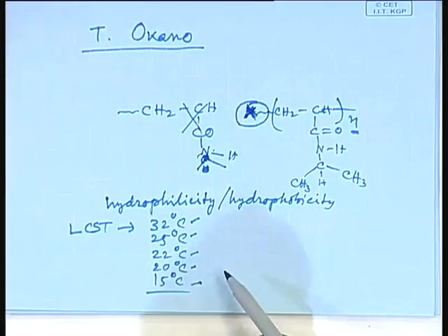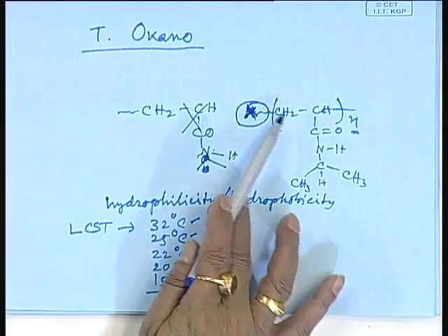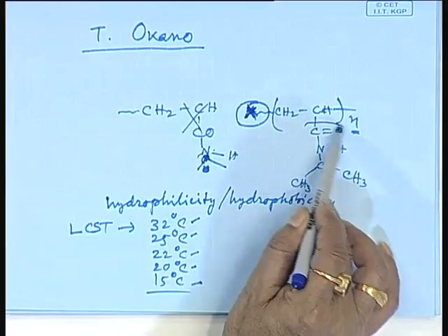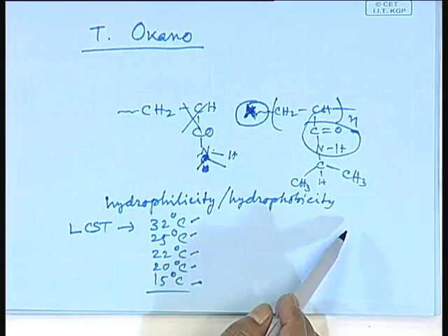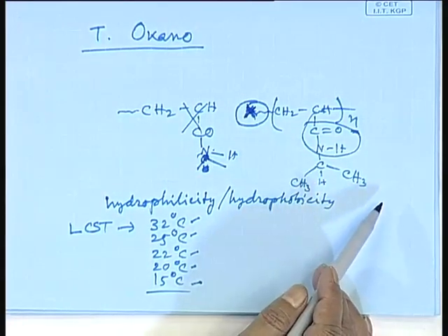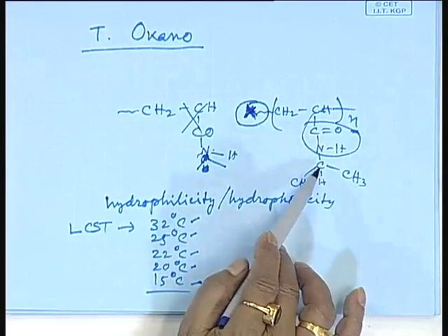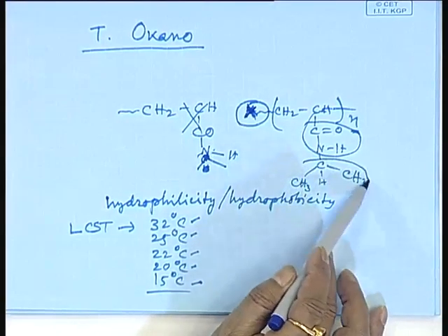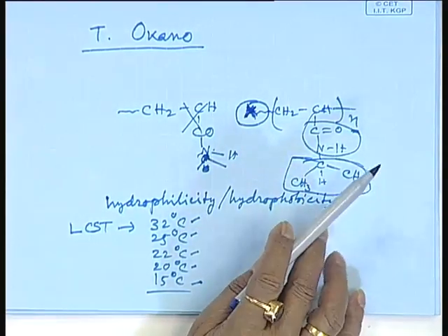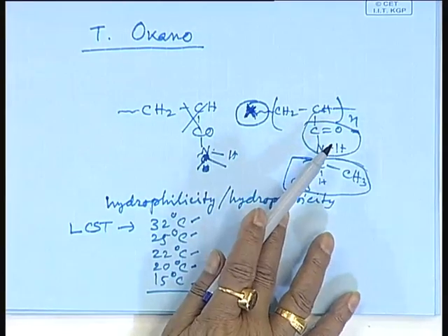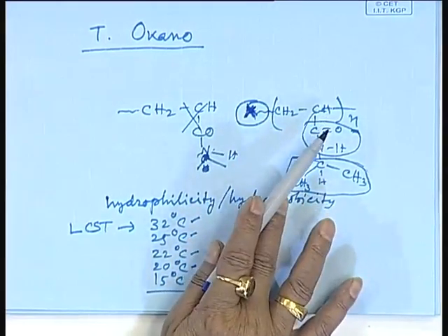So, we have to see what temperature we need, what is the value of LCST requirement, or what is the value of cloud point for that particular application. Knowing that, we can go for proper suitable synthesis for this kind of polymer preparation. Shrinkage is due to the movement of methyl group. Methyl group, that means not only the methyl group but also bending of this backbone chain. That means this portion has to be hidden. To hide this portion, to convert it from hydrophilic to hydrophobic, this portion should be hidden. So, this is not always possible with this isopropyl group. There is contribution from this backbone chain also. So, one could take other backbone, but why has this backbone been taken?